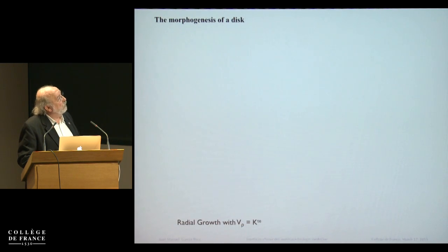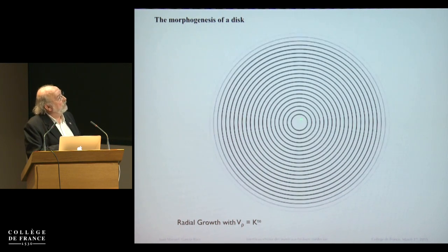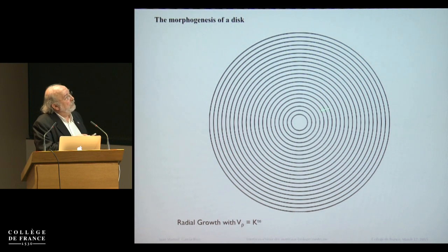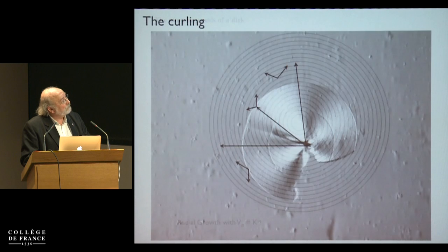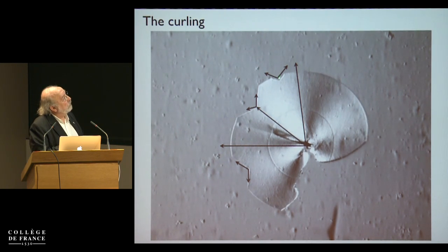So how do the crystals form? Well, in principle, if you have one of these two-dimensional lamellae growing, and the single crystal is in the center of the lamella, then the final form will be a disc, obviously, because you have a radial growth, and in this radial growth you have similar, identical velocity independent of the angle, right? And therefore the final shape will be a disc. However, if we observe the phenomenon with optical microscopy, you can see that there are some singular points in this growing disc, singular points at which the structure stops growing, and then produces this kind of shape.